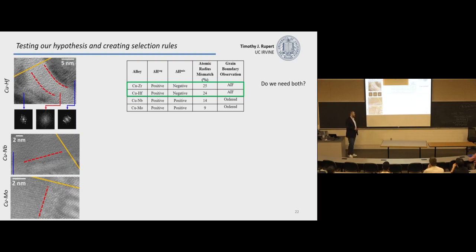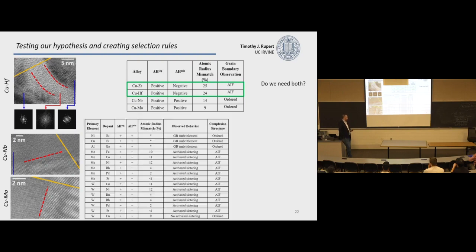We could ask ourselves if we need to do both. We weren't able to really test this with our own experiments, but we were able to more easily go back and look at the literature and find evidence to address this. So people didn't realize it at the time, but as we start to build this idea of what the ordered and disordered grain boundaries do, we could find that grain boundary embrittlement is typically related to ordered grain boundary structure and activated sintering.